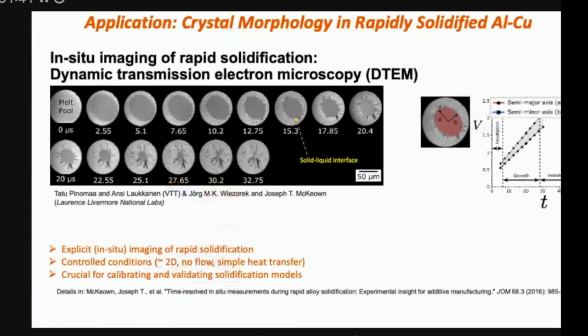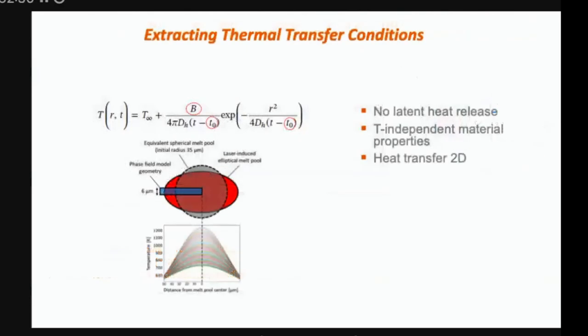It's about 100 nanometers, maybe a little thinner. So it's not truly 2D, but it's pretty 2D compared to the micron scale drop size. So what we did is we took the thermal profiles that correspond to modeling the experiments because you can't actually measure the thermal profile. You measure your laser power, your time of being on and off, and they measured some kind of temperature profile as shown. The different colors represent time. We inserted this into our model.